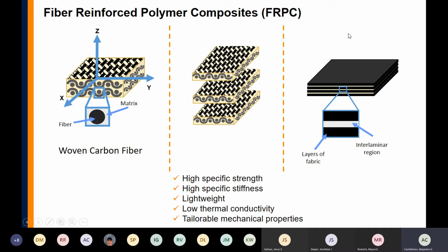The problem, or the challenge that we have right now, is what's going on with the interlaminar region. The interlaminar region is a resin-rich region between each of the layers of fibers of the composite. This part is very susceptible to damage, and that resin-rich region is always a big problem. When we have different failure mechanisms in composites, they usually start with delamination, which is the separation of the layers due to that interlaminar region, which is just a resin-rich region.